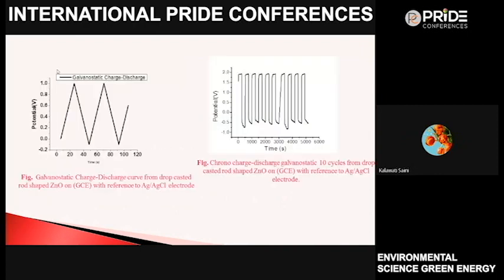These are the galvanostatic charge discharge curves when rod shaped zinc oxide is drop casted on a glassy carbon electrode, and the silver chloride electrode is used as a reference electrode, and these are the different 10 cycles with respect to the Ag/AgCl electrode, and the time taken is 6000 seconds.